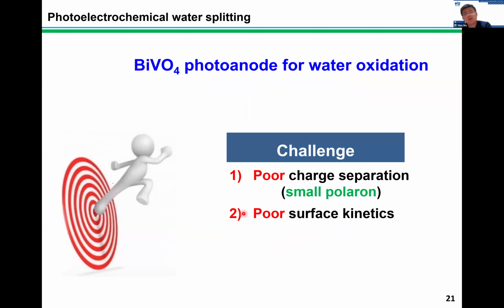And in this area, particularly for water oxidation, bismuth vanadate has been regarded as a top performing material. However, its ultimate performance is still limited by the poor charge separation, which is mainly limited by small polarons and also the poor surface water oxidation kinetics. So to improve the performance of bismuth vanadate photoanode in photoelectrochemical water oxidation, we involved small polaron engineering in this system.